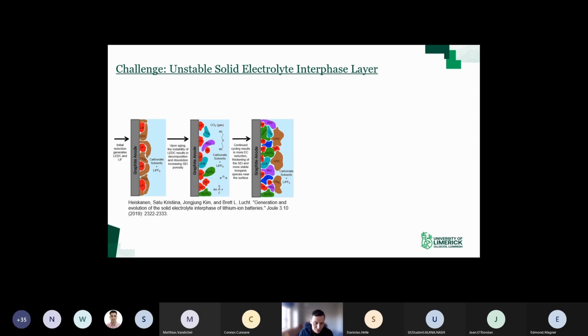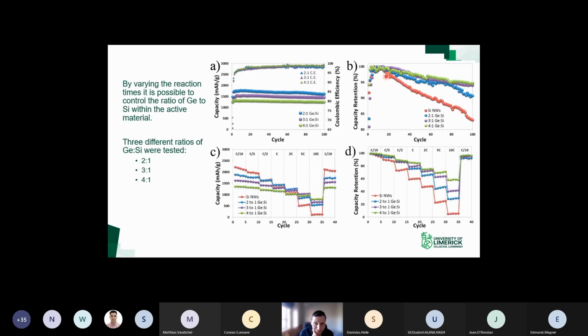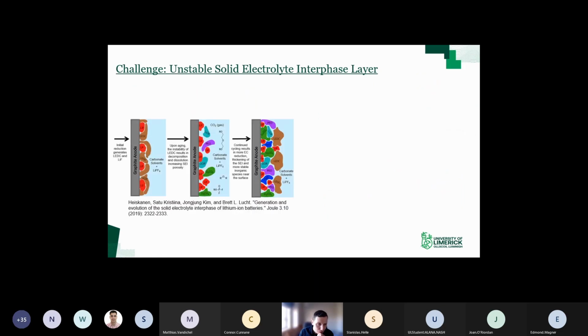One thing, as I've alluded to on the last slide, we ultimately wanted to get to 100% silicon, because silicon is cheap and germanium is very expensive. And also, as I've shown you, unfortunately, silicon didn't have the same capacity retention that germanium had. So while silicon will form that porous, interconnected, stable structure, it still doesn't retain the same capacity that germanium does. So we wanted to tackle that, and we knew the reason for it was the SEI layer, the solid electrolyte interphase layer. Like I said in the introduction, this is a very important component of a lithium-ion battery.